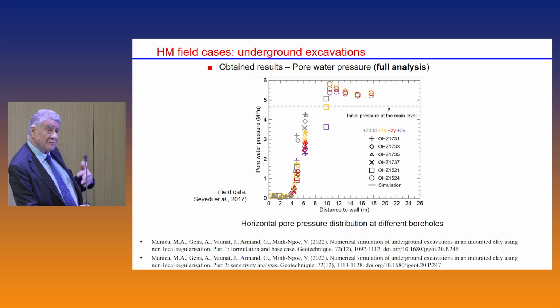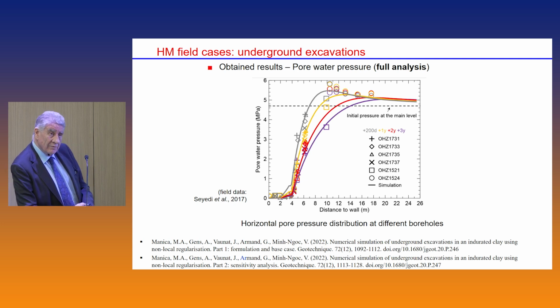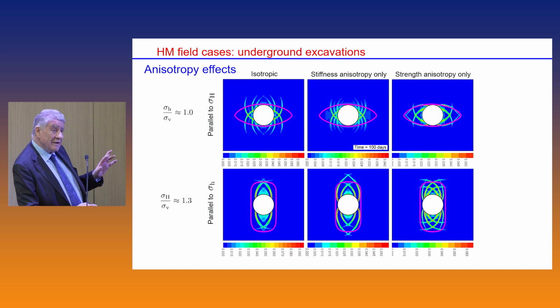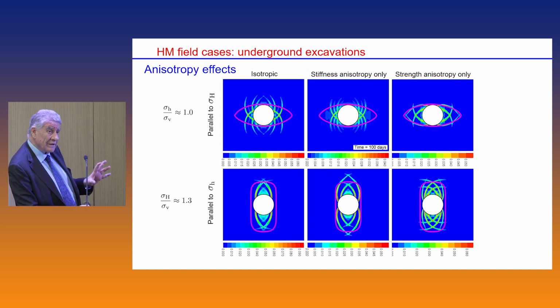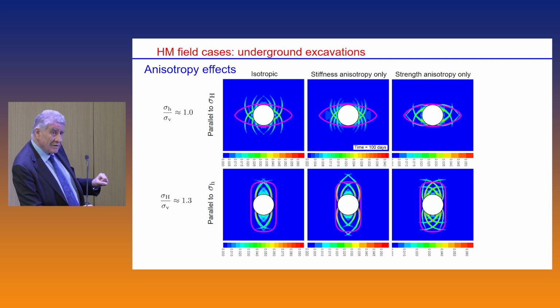In fact, pore pressures were measured at 6 months, 1 year, 2 years, 3 years. These are the results at different times, and again, the model seems to be able to capture this variation of the pore pressure with time. If we believe that the numerical model has some correspondence to reality, one can actually explore the effect of different parameters.